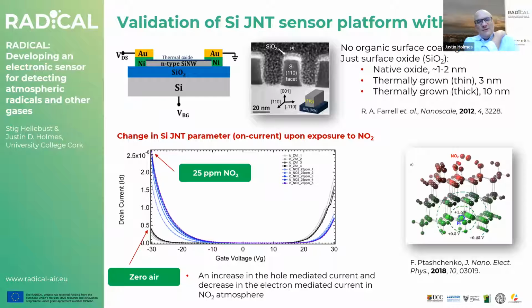This is where we're trying to validate: can we actually see anything with our silicon junctionless transistors, using NO2 as a calibration gas or test gas? If you look at the top left, you can see the type of device we have. We have a silicon nanowire, gold and nickel contacts, and under that a silica layer, and we have a gate. To test our devices, we're not using any organic functional groups on the surface to trap radicals. We're just testing our device with an oxide layer.